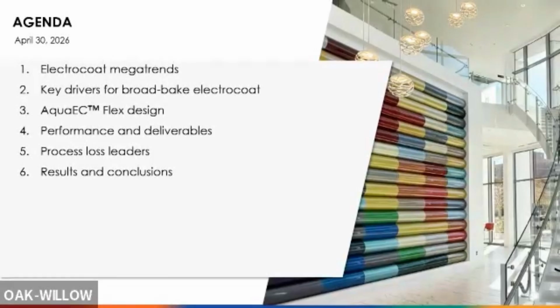We want to improve our coulombic efficiency, which is a fancy term for, as you know, electrocoat, under the influence of electricity, it migrates to the part and then coagulates out and makes the coating that way. It's different from the spray coatings. So our ability to carry that charge and coagulate to the part has to be increased to help efficiency. And then finally, we need to be able to deliver a cross-link dense coating at 140 C. So we're going to talk a little bit about that.